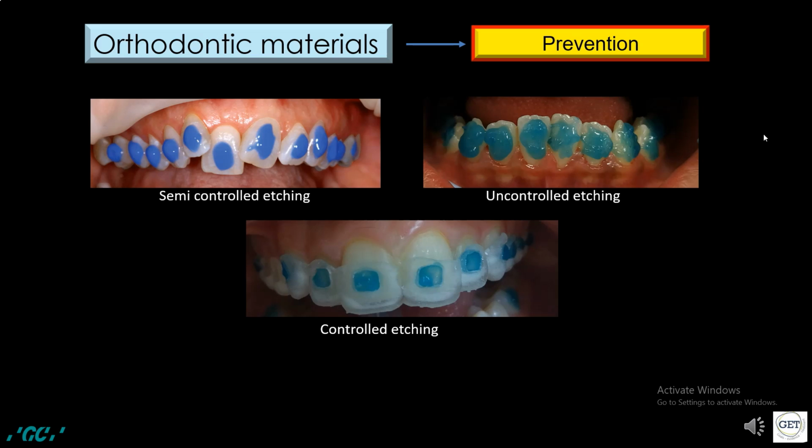The etching of the enamel, according to the literature, is reversible, as the enamel takes up the required calcium or fluoride from the mouth environment. But also by research, the etching time is important. Overtime is proven to cause irreversible damage, and the mouth environment can be not very ideal, for example the level of acidity and the presence of pigments.